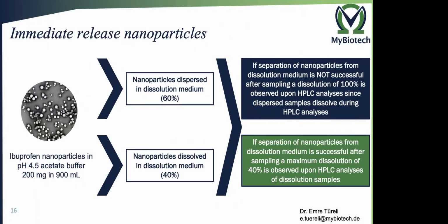So when we take 200 milligram ibuprofen nanoparticles and put them into 900 milliliter pH 4.5 acetate buffer, two things can happen. In the first place, the complete nanoparticles are dispersed in the medium. Then approximately 60% stays dispersed in the dissolution medium, and 40% dissolves in the dissolution medium. That is the difference that I want to quantify in a dissolution method, to be able to say if the nanoparticles are dispersed, dissolved, or if it is happening at the same time.